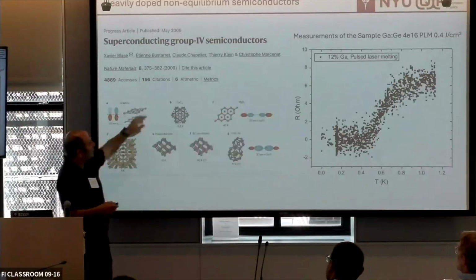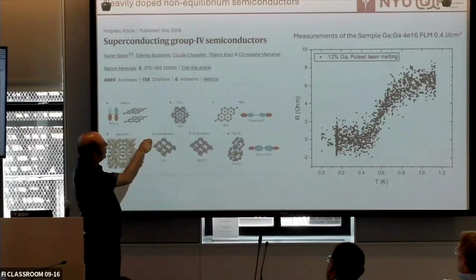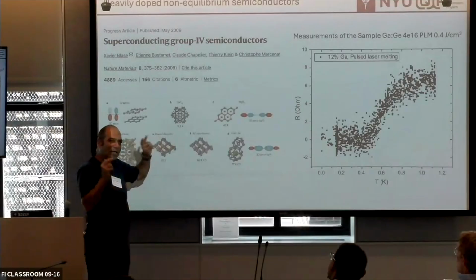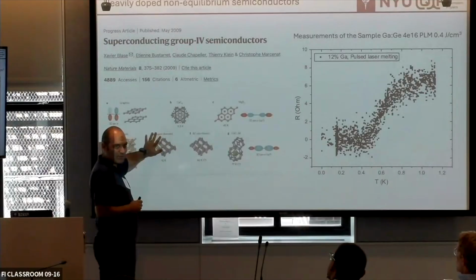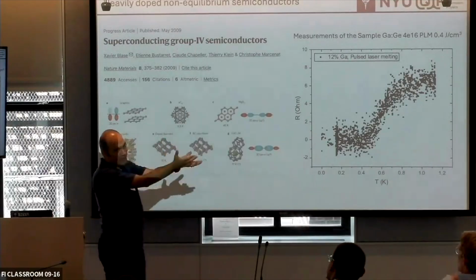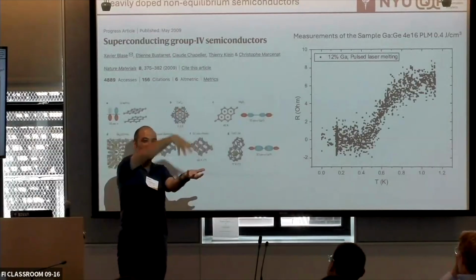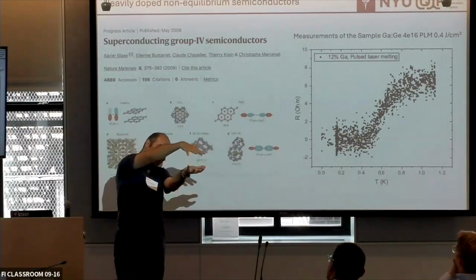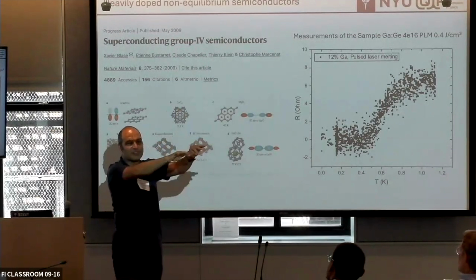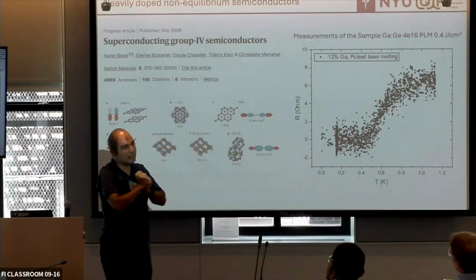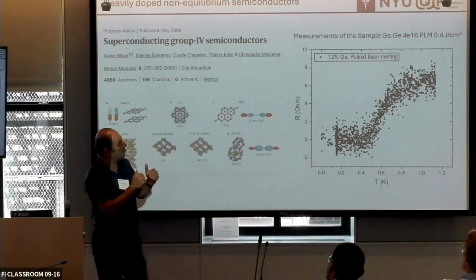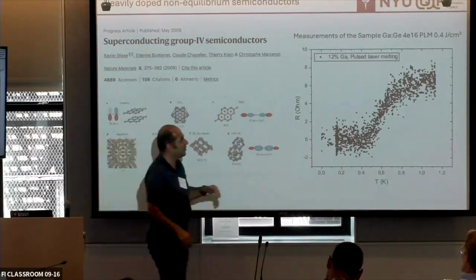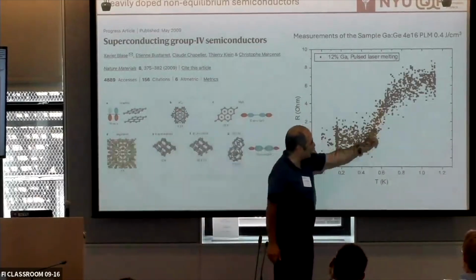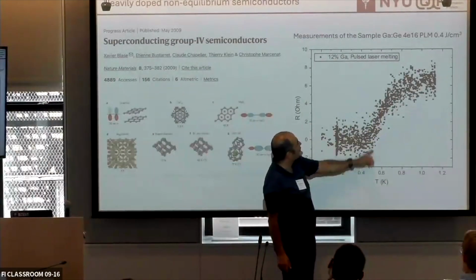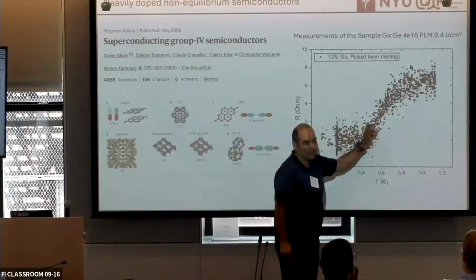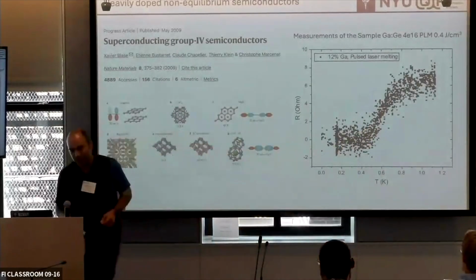So basically, if you can brute force make superconductivity in group 4 by non-equilibrium doping, that was the story in 2010. So you basically melt silicon, you put, let's say, gallium or boron on it, and then as you recrystallize it, the boron somehow goes inside, and then it gives you a superconductor. Various temperatures. If you look at it with STM, everything kind of comes to the surface. You see a trace that is scattered. This particular one, I guess, is gallium and germanium, about half a Kelvin superconductor, right?